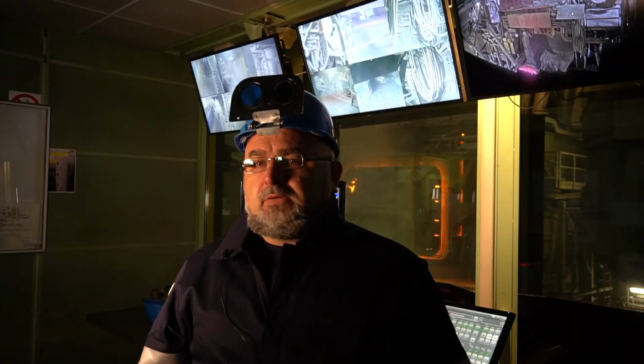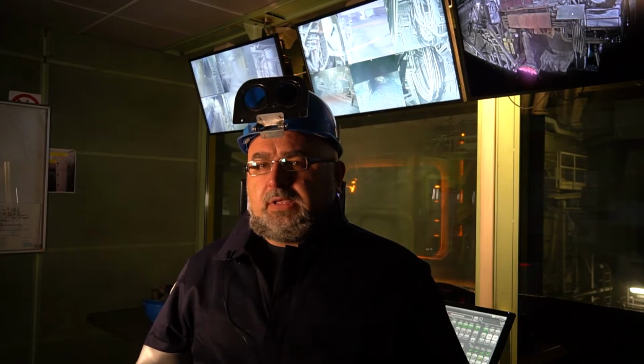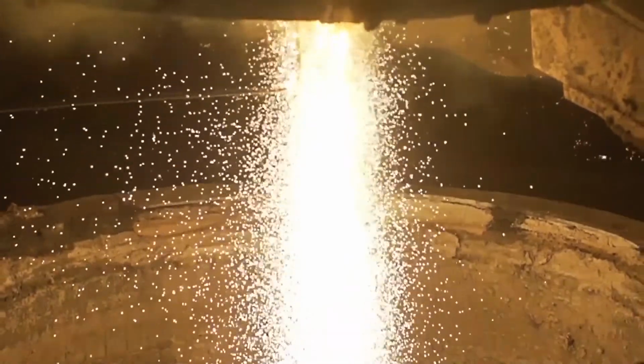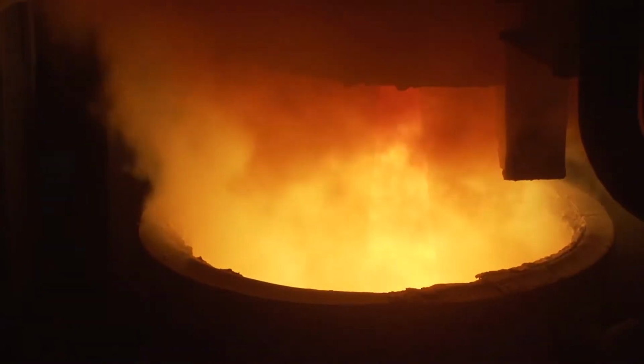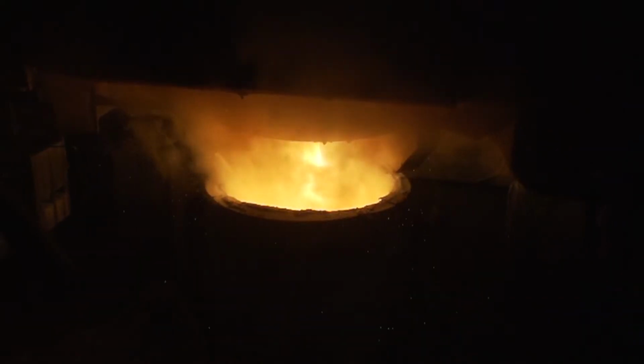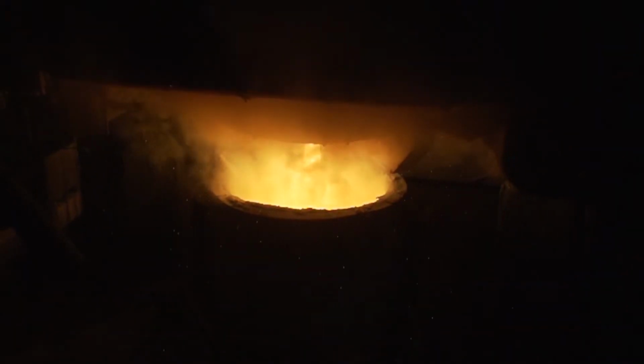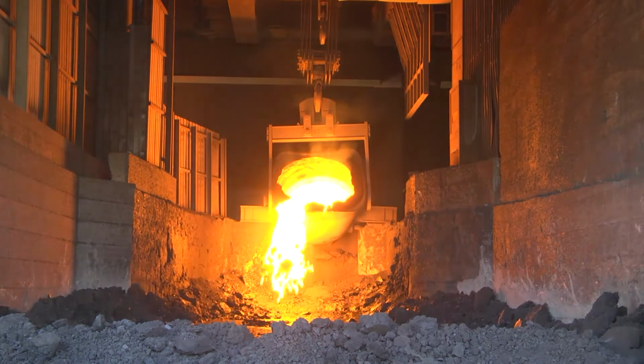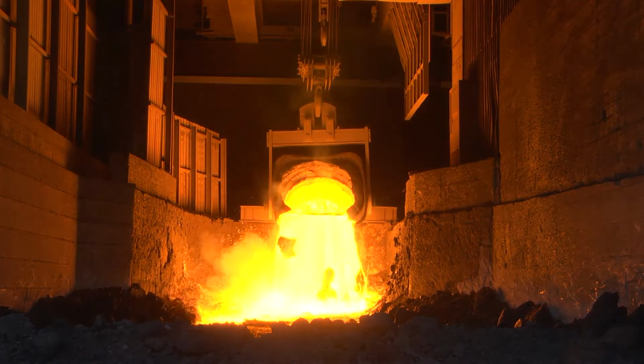An important part of steel making is the formation of the slag, which is a mixture of oxides with a lower density than the liquid steel. The slag that forms floats on the surface of the liquid steel, and before tapping the steel into the ladle at a temperature of 1620 Celsius degrees, it pours out from the slag door.